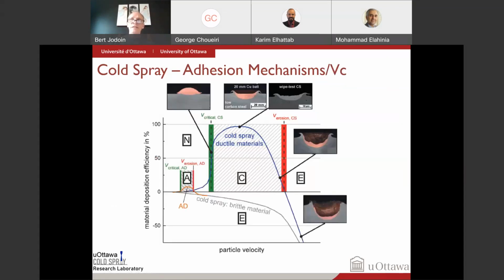If I summarize a little bit here, don't worry, this is very crowded, but let's just focus on the blue line here. On this axis is the particle velocity at which it impacts the substrate. Here is the percentage of particles that will stick at this velocity. So if you throw the particles at low velocity, they don't really stick. Then at one point, some of them will stick, maybe because some of them have a thinner oxide layer and you can really break it. And you can clearly see a big ramp up at one specific velocity where most of them will adhere.